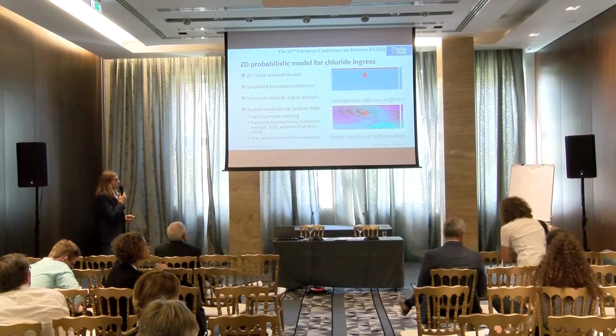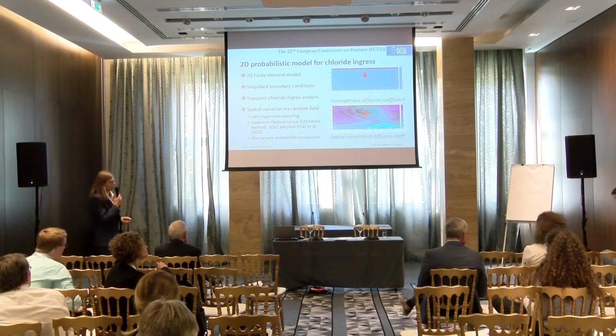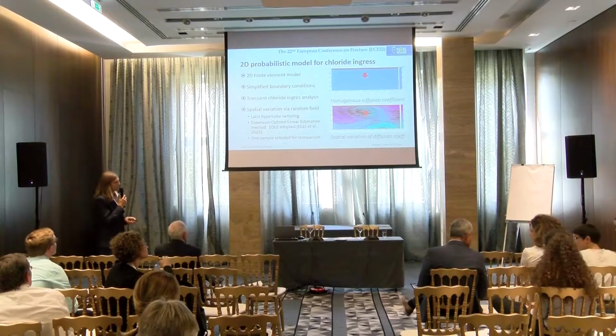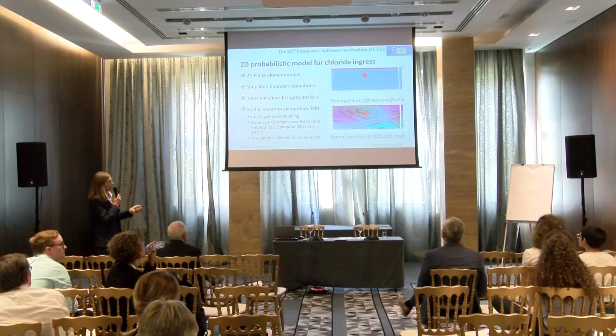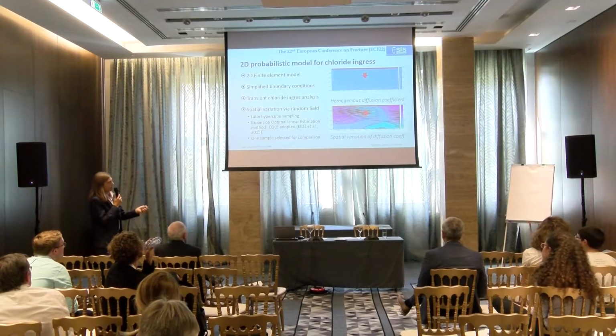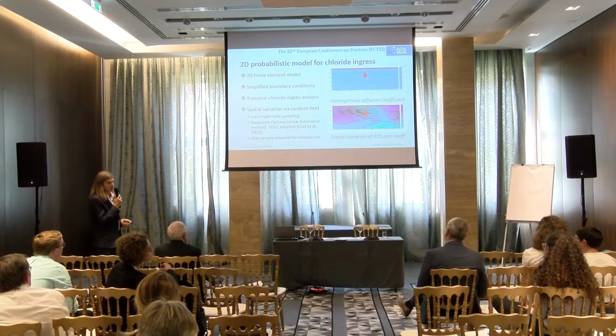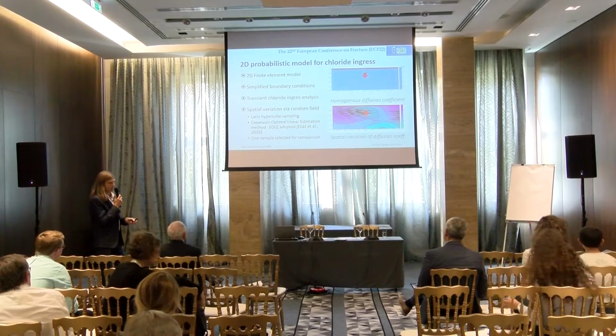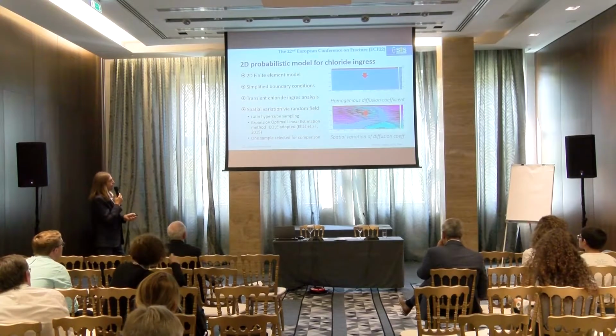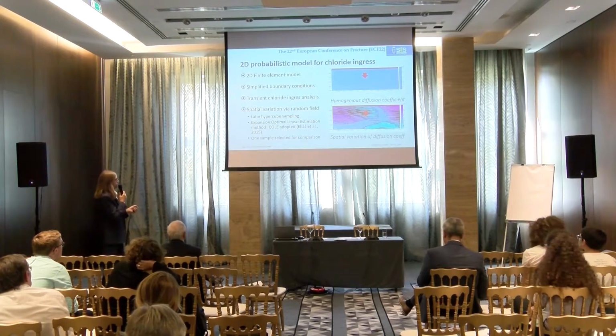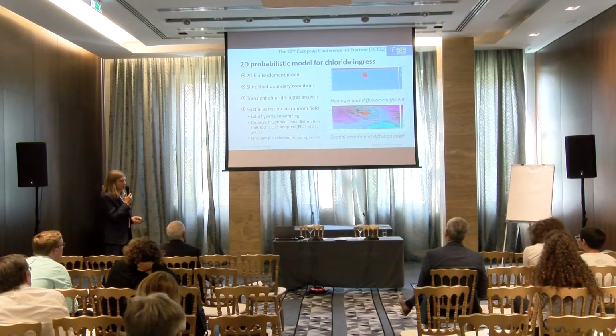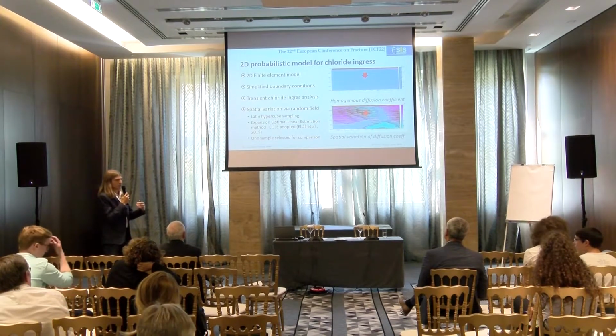For that test, we used the finite element analysis, and the boundary conditions were simplified, so the chlorides were approaching from the surface only. So we have not dealt with the crack effect here. And it is a transient analysis. It changed over the time.